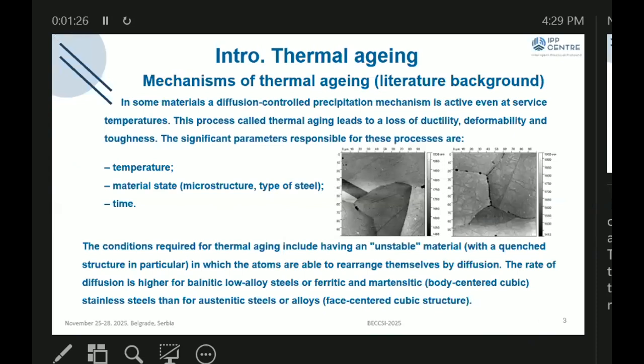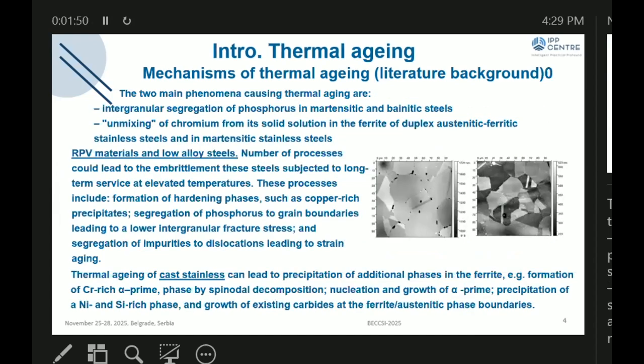In some materials, diffusion-controlled precipitation mechanisms are acting even at service temperatures. This process is called thermal aging and leads to a loss of ductility, deformability, and toughness. The significant parameters responsible for this process are temperature, material state, and time. The two main phenomena causing thermal aging: the first is intergranular segregation of phosphorus in martensitic and bainitic steels, and second, unmixing of chromium from solid solution in the ferrite of duplex austenitic-ferritic stainless steel and in martensitic stainless steel.